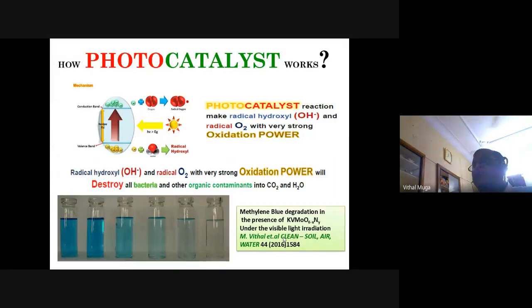Further, he has done a few more things, but just to demonstrate how the photocatalyst works, we take the methylene blue, add the catalyst, and irradiate it. As a function of time, if you measure its optical density, we will see at the end of the 180 minutes, it is almost more than 90% degraded. How can we practically apply this? Let us say that in Hyderabad, we have Hussain Sagar, which is highly polluted. In fact, one of my students went to Hussain Sagar, and with great difficulty, closing his nose, he obtained 2 liters of water. Now, having got the Hussain Sagar water, we need to address this with reference to our catalyst.